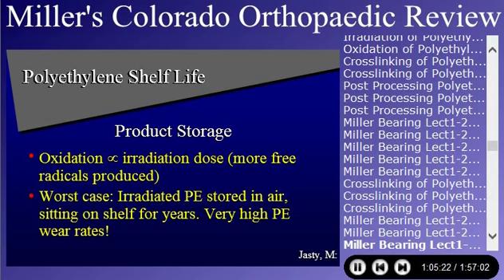Murali Jasty showed that if you have these jumbo cups, size 72 jumbo cups sitting on the shelf for 5 or 6 years, and they're irradiated in air, and they sat on the shelf for 5 or 6 years, those bad boys wore out in 4 or 5 years because they're completely oxidized on the shelf. So you've got to be very careful about your shelf storage life, especially in what we call odd lot sizes, i.e. very small, very large